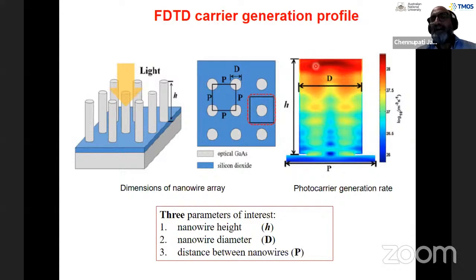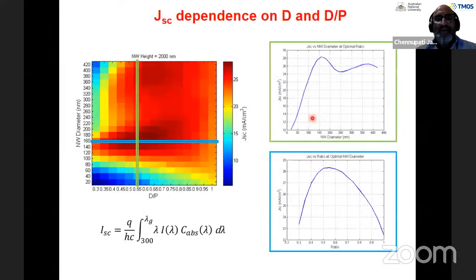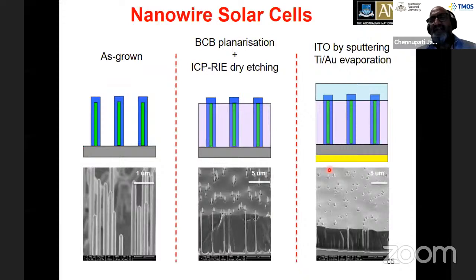This is an example for a gallium arsenide nanowire or indium phosphide nanowire, for example, in this case here. We've also looked at the diameter of the nanowire, and again, under optimum conditions, the highest current you get is for nanowires which are about 150 to 160 nanometers in diameter, and a diameter to pitch ratio, pitch is the distance between the nanowires, of about 0.5 or 0.6. You can see 0.5, 0.6 is the maximum current being generated here. Again, these simulations play a very important role in making any of the devices using these nanotechnologies.